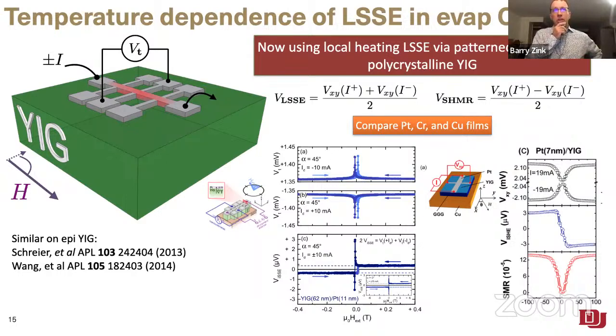And they went off and thought about it and worked on it for a while, and they came up with a much better idea. They actually read some papers in the literature, and they said, well, why don't we just do this with local heaters and everything made via e-beam lithography? And I thought, that's a better idea. That's much more our style of stuff. And so this is what you do. They've implemented some already developed techniques to measure what I'm calling the local heating longitudinal spin-Seebeck effect. And this is relatively simple. You make a Hall bar on top of the magnetic material that you're trying to probe. In this case, we're still working on polycrystalline YIG.